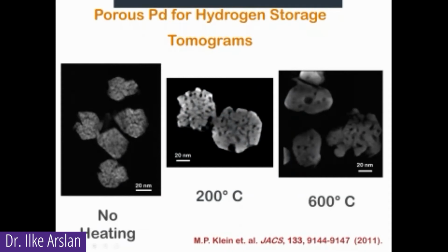So as you start heating them up, it becomes unstable for them to be pores in this area. The palladium wants to fill in. So it becomes thinner and thinner in the pore region and gets bigger at the intersection regions until it snaps and just becomes a bubble. So this work allowed us to understand that we had to form the particles in a different way. We had to synthesize the pores in a different way in order to keep them stable.